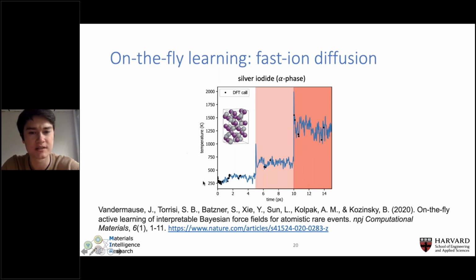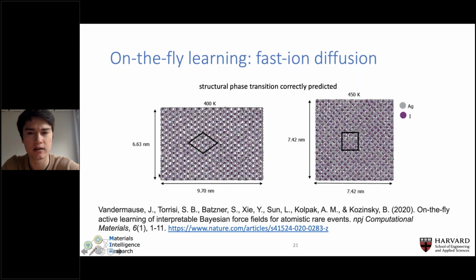So we went through this three-stage training process where we cranked up the temperature in an on-the-fly simulation at 2 different stages. And you can see the black dots again are every point at which we made a call to DFT. And then we took that final model and we ran sort of big simulations of about 10,000 atoms at various temperatures. And you can see here that we're sort of correctly modeling the 2 different phases that are sort of experimentally known to appear in this material.